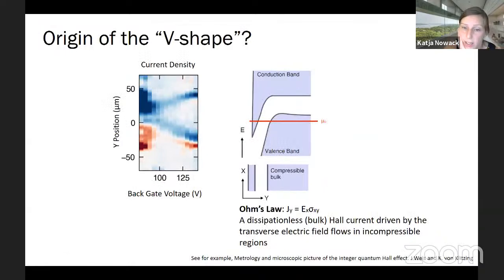This is one part that is still work in progress: how we're approaching understanding this V shape and what is going on. What we think is going on is that there's band bending present in the device, and that we tune the Fermi level through a structure as is schematically shown here. What I think happens is that the whole current that we visualize is really flowing in the incompressible stripes that form within the sample. And there's a clear evolution, as we tune the Fermi level, of where and how wide the stripe is within the sample.